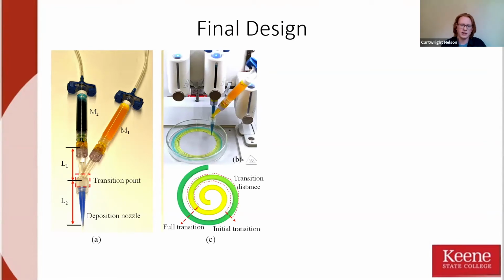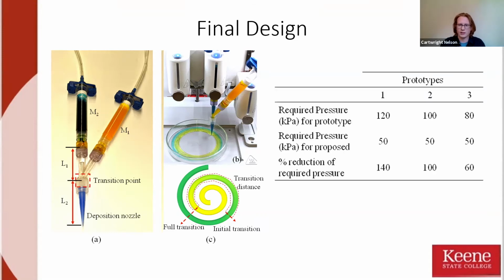And to test the transition distance, like I said, I modeled a spiral, and by measuring the print speed and the time it takes to transition, I can find the transition distance. So you can see how it would be preloaded with one material, and then as it starts printing, it switches to the other material, and the time that this takes to clear all the way out and start printing the other material is recorded, and that is the transition distance. So to minimize this, I'm working on shortening that mixing chamber length, and also testing many different parameters.